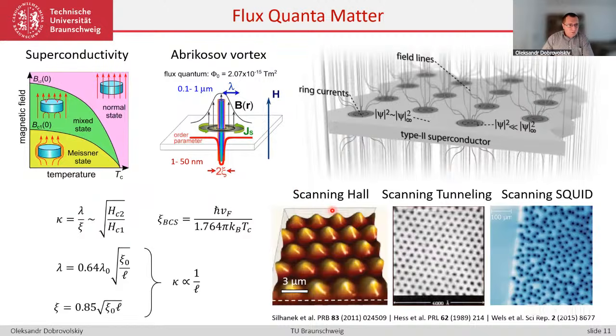The presence and configurations of the vortex lattice have been visualized using various experimental techniques, including scanning Hall, scanning tunneling, scanning SQUID microscopies, and many others. In many cases, one deals with an ordered vortex lattice as here, where you see almost like a vortex crystal. But because of interaction with edges, with imperfections, with defects, with pinning sites, there can be a deviation from a perfectly ordered vortex system. So one has an array or ensemble of vortices, but this ensemble doesn't necessarily possess long-range order. And this will be crucial for the content of my talk, because we will need to ensure very high crystallinity of the vortex lattice when we're talking about coherent fluxon-magnon interaction.